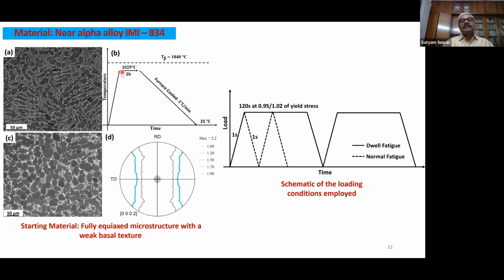It's a disc alloy. So we have just carried out the deformation and annealing, basically annealing, and that generated this type of texture. We can see here that this is a very weak, weak basal texture, and a fully equiaxed microstructure. Initially we wanted to gather information where this beta phase, which is seen here, should not intervene in our interpretation, so that we can get pure information about just the orientation and alpha-alpha boundaries. But in alpha-beta alloys, we do not generally see alpha-alpha boundaries. Generally it is alpha-beta boundaries that we see, because beta has a very high propensity of formation at the boundaries of two alpha grains.